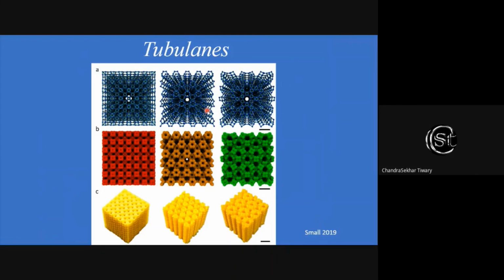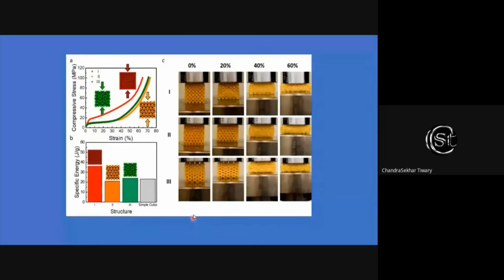They are topologically complex, and they don't have any single flat surface. They are all curved all over. And once we created the structure, we printed it, and again it shows a lot of excitement in terms of mechanical deformation. For example, it is directional, so you can control the deformation depending on the requirement. Even the fracturing takes place in a certain direction and so on. All these can be tuned in the structure.